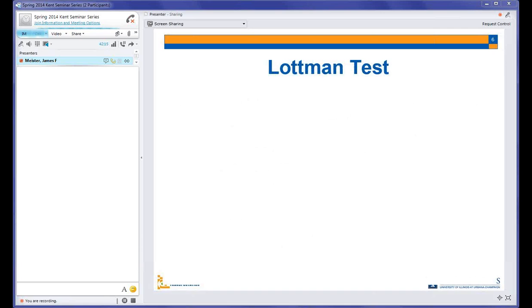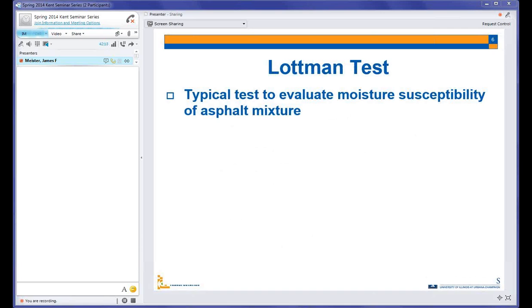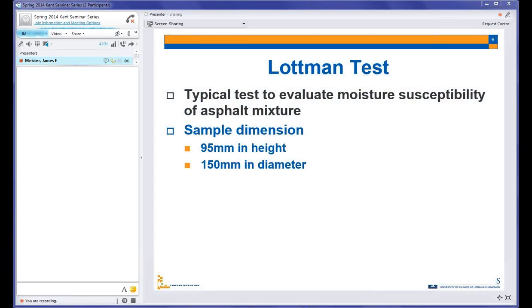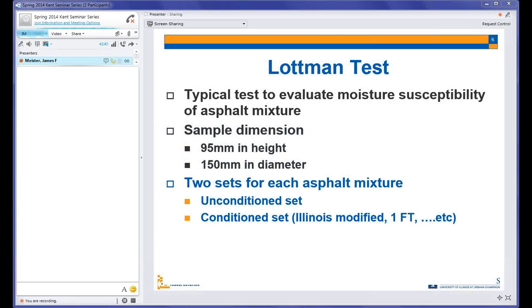So what is the Lottman test? The Lottman test is the typical test in the US used to evaluate moisture susceptibility. Most transportation engineers know that this test is used in different agencies to evaluate the moisture susceptibility of asphalt mixtures. Usually the dimensions of the sample used for this test are 95 millimeter in height, 150 millimeter in diameter. For each asphalt mixture, we usually prepare 2 sets.